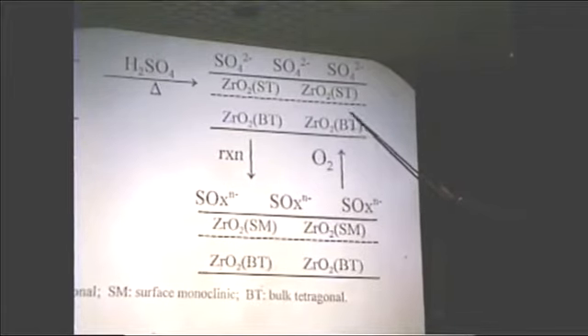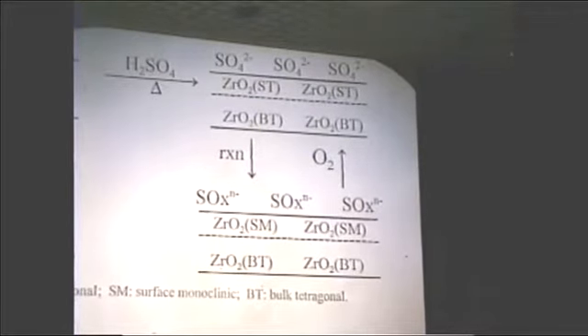So on the basis of this, we propose a model that involves a surface transformation of the zirconia under reaction conditions from a case where both the surface and bulk phases are tetragonal form to a case where the surface phase is now in the monoclinic form, possibly because the sulfate groups are reduced, or there's clearly some interaction between the sulfate groups and the zirconia. And then the oxidation returns the zirconia back to the tetragonal phase.